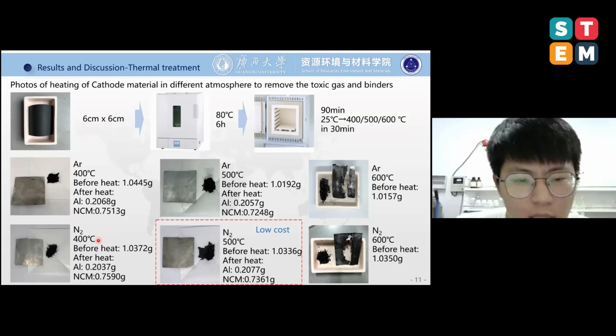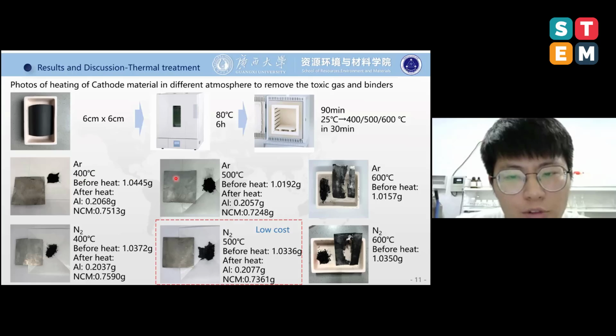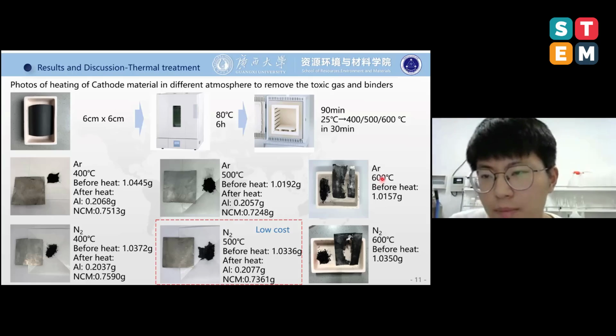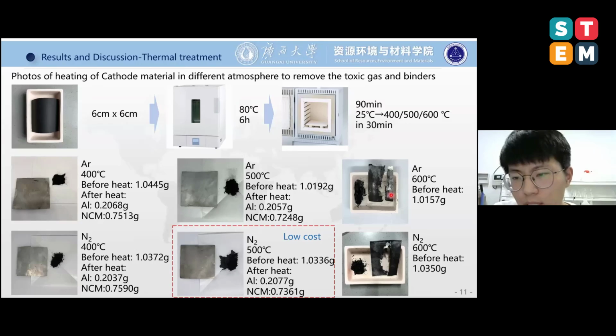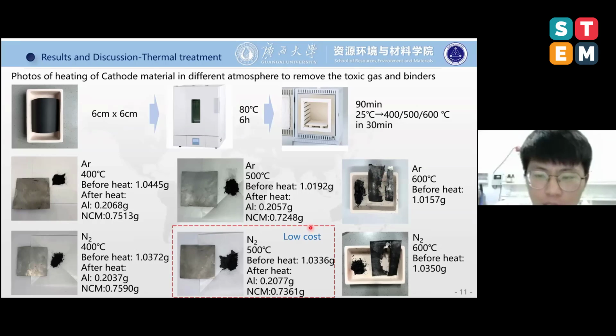For the argon atmosphere and the nitrogen atmosphere at the temperature 400 and 500, we can separate cathode material and alumina very well. But when the temperature is 600 in argon or nitrogen, something happened. The cathode material was destroyed. We cannot separate cathode material, cathode black powder, well. And considering the price, we use the nitrogen as the atmosphere to separate the cathode black powder and aluminum because it is cheaper than argon.